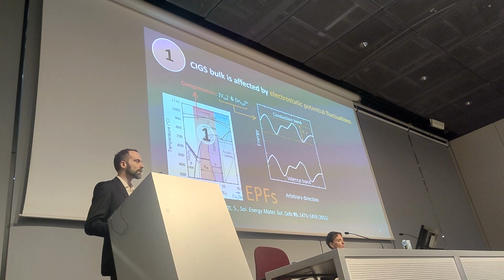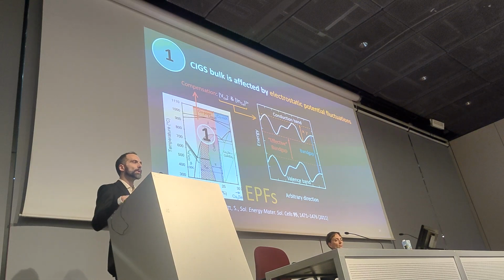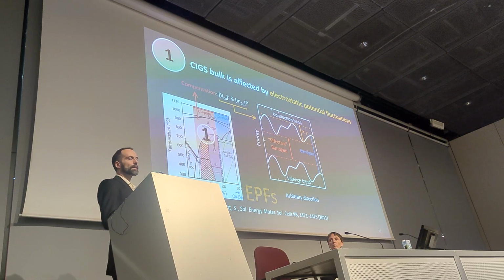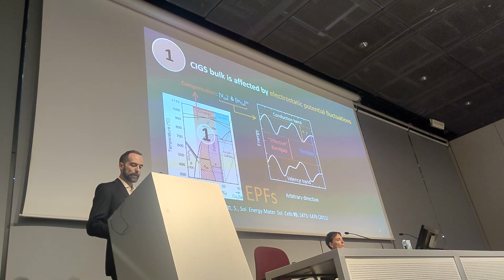You may wonder if this has a consequence or not for the technology. It does. Because what happens now, the bandgap of the material is unchanged, officially. But effectively, it's as if we had a smaller bandgap, because the photogenerated charge carriers perceive a smaller bandgap. And since the open circuit voltage of the device is proportional to the bandgap, what we end up with, effectively, is a drop of efficiency when we make devices.